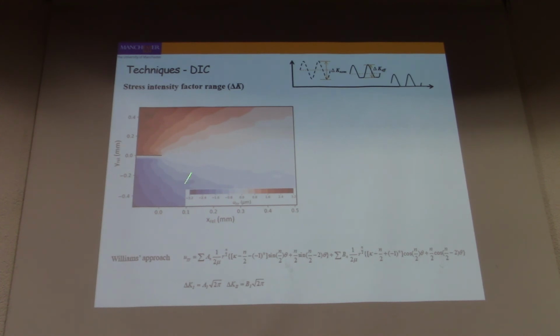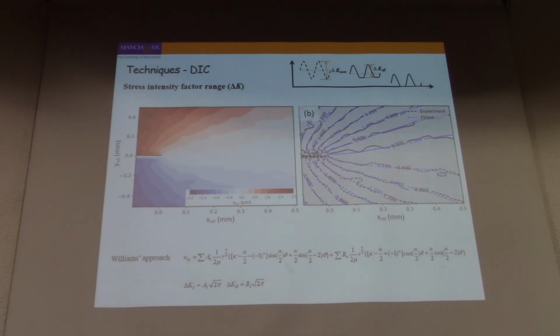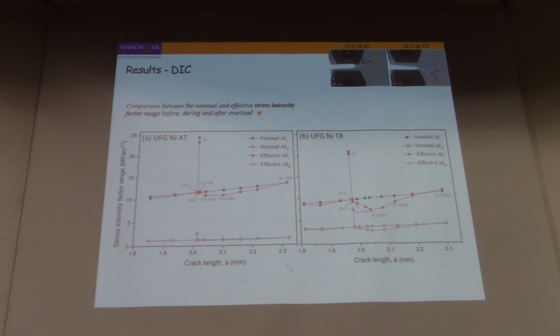Similarly, we can also fit the displacement field with Williams' approach, and we can observe that the stress intensity factor range for the TR case is more reduced.